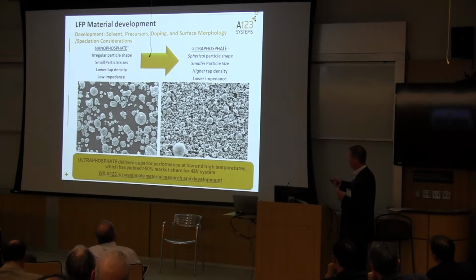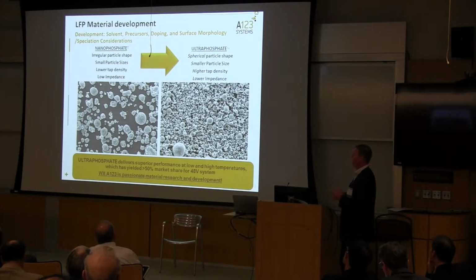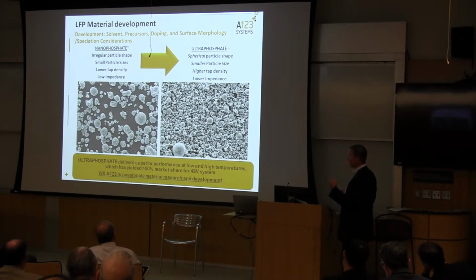And so you could see from some high-level SEMs, we go from something that looks like this to something that's very compact, very spherical, and very controlled, all the way down to the primary particle. And so really, we had our irregular particle shapes, smaller particle size. The tap density was not very good, and the impedance was low. But now we could go to very dense spherical particles. This is very important for processing. Even smaller particle size at the primary particle, because this is a first order phase transition, so you want the characteristic lengths to be as short as possible, and then this resulted in much lower impedance.